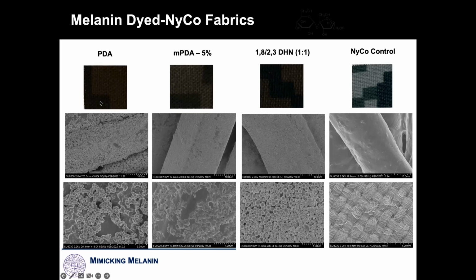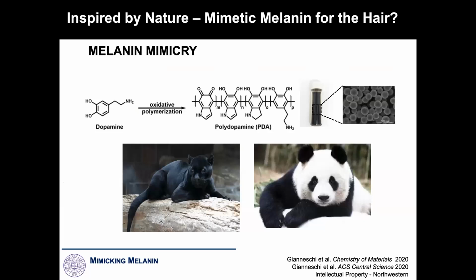What we did was melanize it. So in other words, we dyed the fabric. And you can see here on my screen, hopefully you can see it. These are darkened, but you can kind of still see the camouflage underneath. When we look at the SEM images, we can actually see that the fibers are intact. They're not frayed, which is nice. So the fabric still has integrity, it's fully intact. So you can see here a zoomed-out image of the woven fabric, but we've dyed it. As a little segue, of course, this is exactly the way that the fibers in our hair and of course those of jaguars and pandas are also colored like that. Of course, the white fur is another story, but that's the way that works.